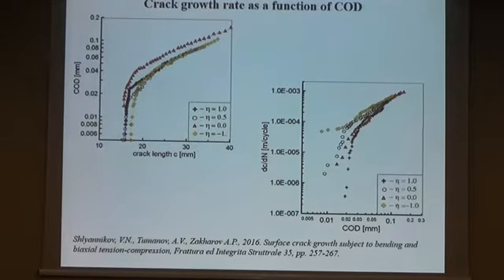On this figure, you can see the experimental data obtained by direct measurements of crack length and crack opening displacement. This figure represents the relations between crack opening displacement and crack length on the free surface of specimen. And this figure represents the dependencies between crack growth rate on the free surface of specimen and the crack opening displacement. And you can see that in the first stage, when the crack propagates like a surface, semi-elliptical crack, there is a significant influence of type of biaxial loading.